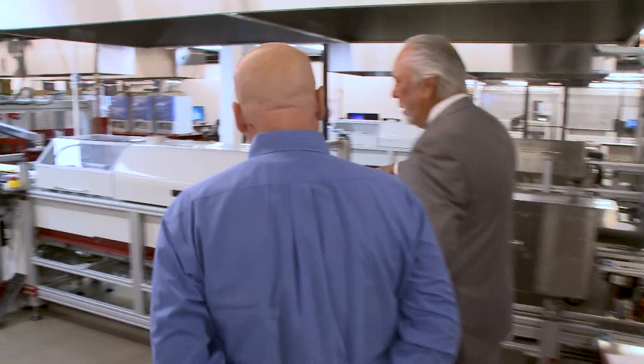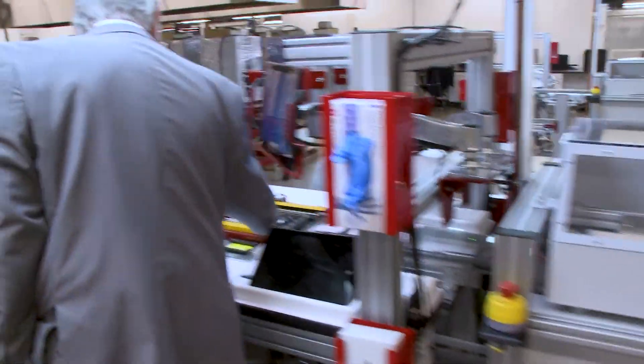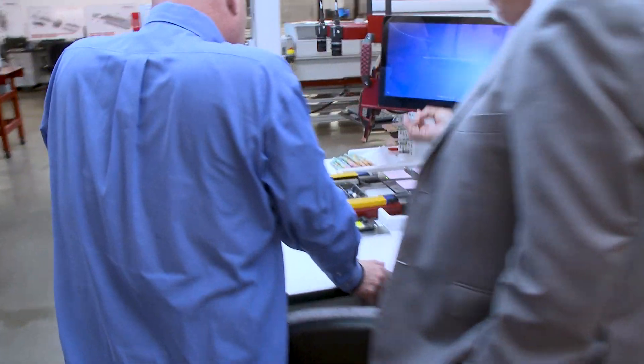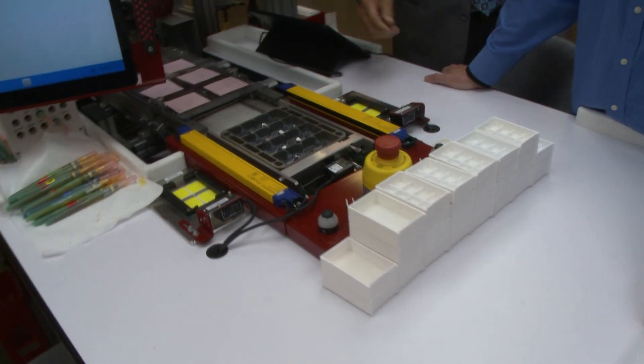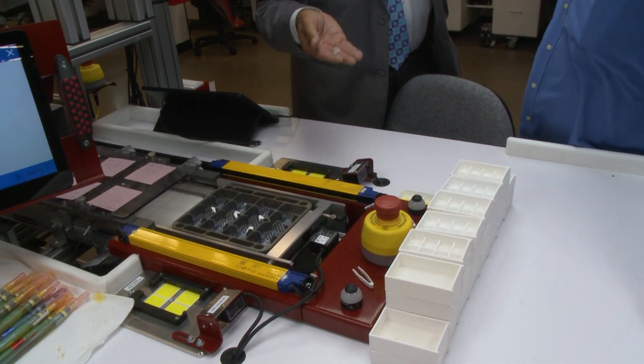When the units come out, they go through a system and are placed in little boxes. Those are anteriors coming out — they're 21% oversized. This is not solid zirconia yet; it's just a porous powder that has to be shrunk down 21% to reach accurate size. Chairside, you can mill a Bruxer crown in about 12 minutes because it's 100 megapascal in that state, but solid-state zirconia is 1,200 megapascal — you need diamonds and cut slowly. Small crowns take about 36–38 minutes; bigger ones take 42 minutes. But after 42 minutes, you go directly into the mouth.